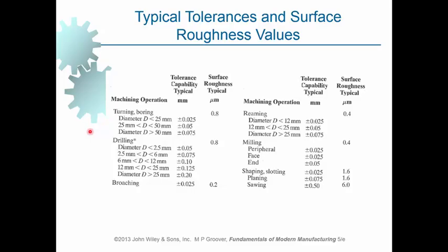And the other thing that we need to take into consideration is that if we assign a tolerance that is tighter than what is given in this table, it means that we may need to introduce additional machining operations to achieve the assigned tolerance or surface roughness. What is meant by this is that if, for example, we are drilling a hole of 6 millimeter in diameter on a drilling machine, then the tolerance that can be achieved is given here, that is plus and minus 0.1 millimeter. This is something that can be achieved, and the surface roughness that can be achieved from this is given here, that is 0.8. Now if for the same hole, a hole of 6 millimeter in diameter, we assign a tolerance that is tighter than this range, say for example 0.025, then what happens?